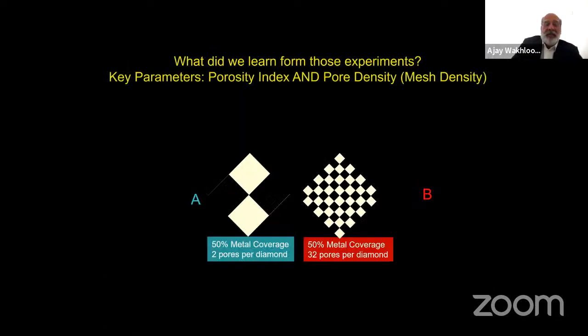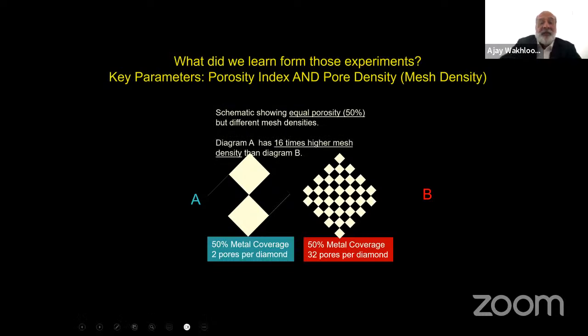What does that mean in lay terms? In lay terms, if you look at this checkerboard and you see black and white, the ratio will be 50. So here, the metal coverage would be 50% or porosity of 50. And there will be two pores per diamond. On the right side, you have the same ratio of black and white of 50%. The difference only is that you have 16 times more black and whites on the right side. That's exactly what mesh density or pore density means. While the porosity in both of them is 50%, the pore density or mesh density is 16 times higher in the right than in the left side.